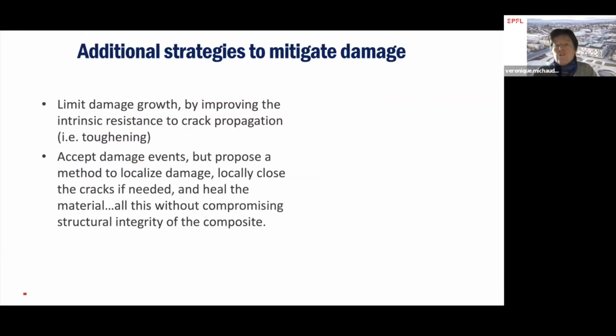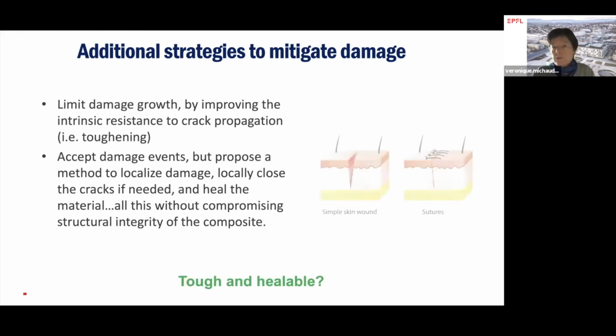Now, what are the additional strategies that we can use to mitigate damage? Of course, there is a lot of research on limiting damage growth by improving the intrinsic resistance to crack propagation, for example, with toughening matrices, or different design variables that can be changed to improve the resistance of the structure. But another possibility is to accept that you will have damage events and propose a method that would ideally localize the damage, locally close cracks if needed, and heal the material. All this without compromising, of course, the structural integrity of the composite.